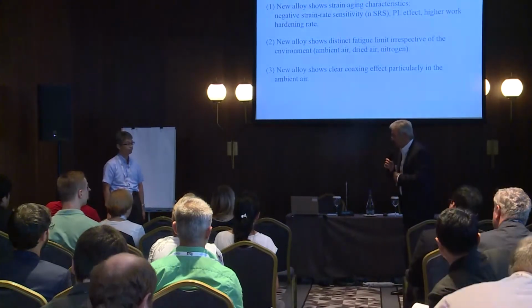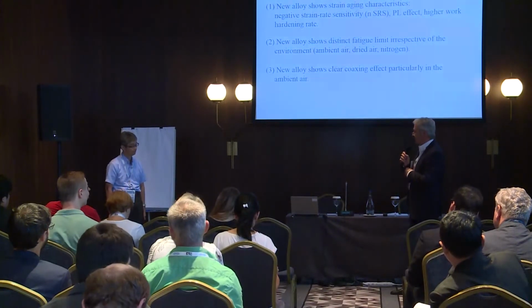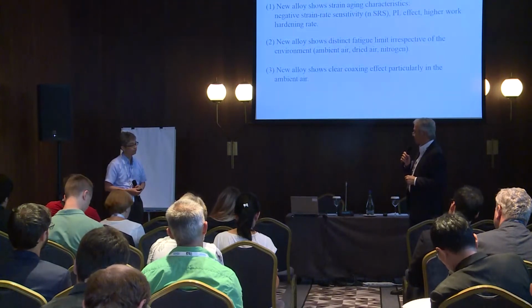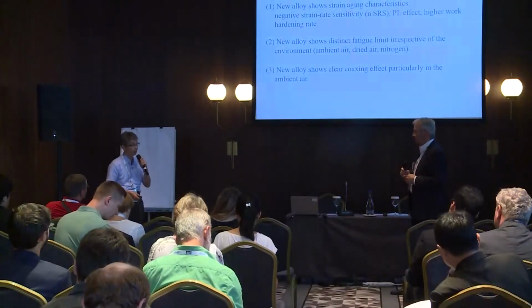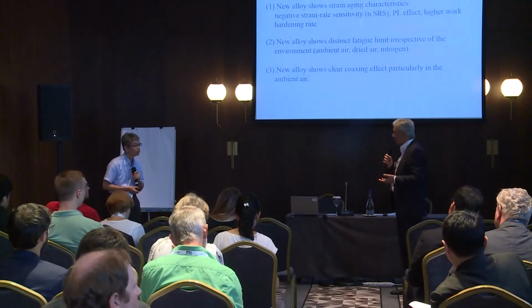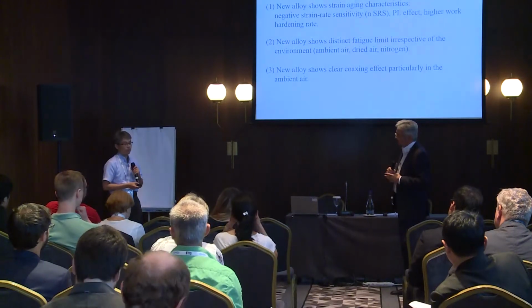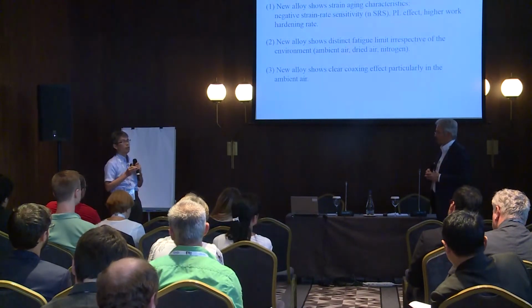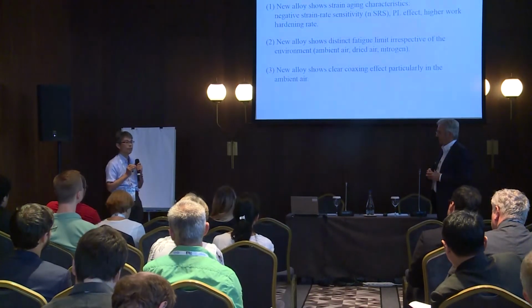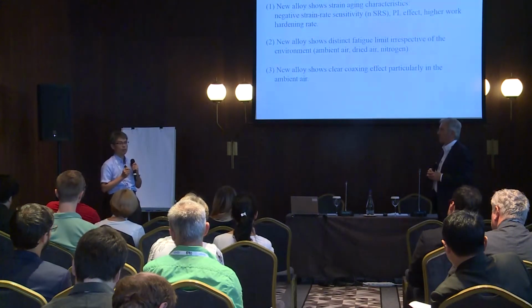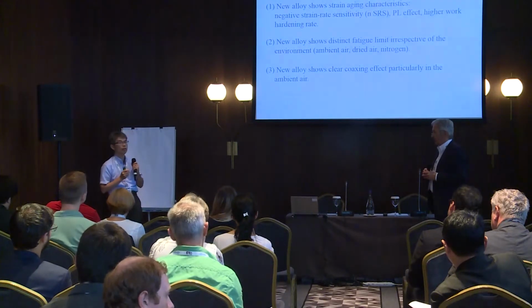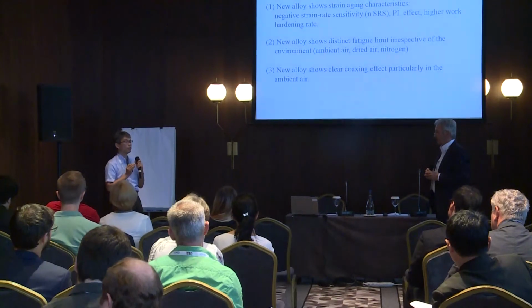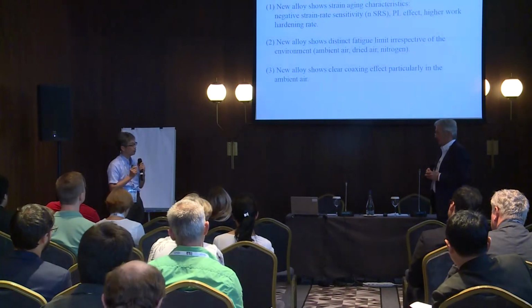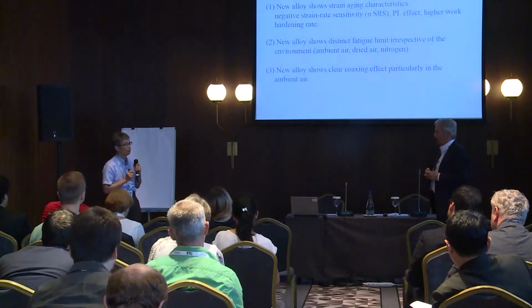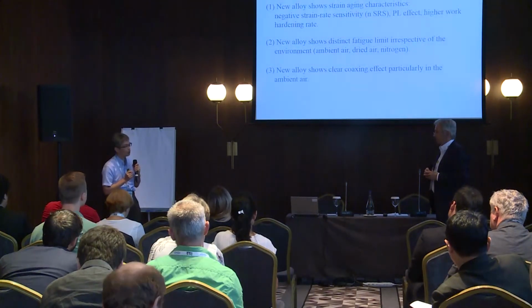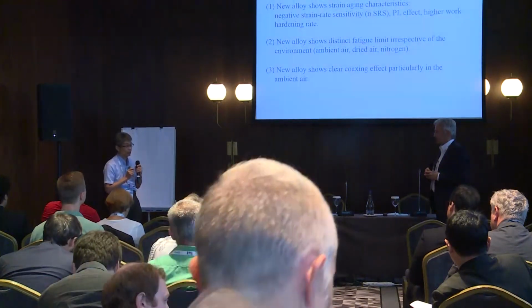So the fatigue limit is certainly connected to these magnesium atoms, and the obstacle of these magnesium atoms to dislocations, right? Yeah, that's my thought, I think so. And you think that could be also the reason for this environmental effect, which you questioned at the end? Yeah, it's difficult to answer, but in the ambient air, somehow the magnesium effect is strong. But in the dry air, or in nitrogen, which means that the environment doesn't contain water, they show somehow a weaker effect of magnesium. So I think this is a very important point, and we can analyze this point further in the near future.